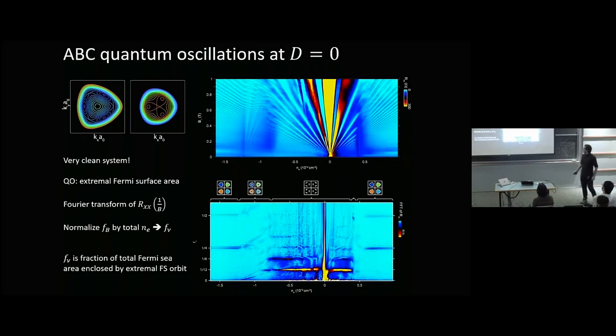And then if you go to very low density, you see that all of this is gone, and now you just have a very strong peak at 1/12. And 1/12 is exactly what you expect at very low density once you're past that saddle point Van Hove singularity. And now you have 3 pockets per flavor, so 12 total. And the Van Hove singularity apparently is right there. And nothing too interesting happens for holes, actually, at 0 electric field.